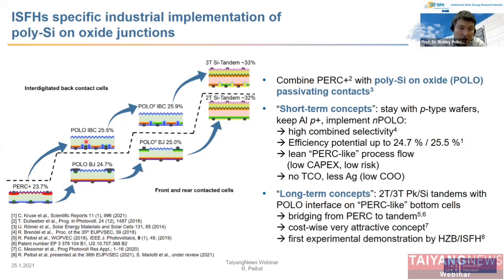And this should enable a high efficiency potential, as shown here with these numbers. Those are numerical device simulations for industrially feasible input parameters, in combination with a lean, PERC-like process flow, and in particular with a low silver consumption, because at least one polarity is still metallized with aluminum. This can be done either in this IBC version or in this double-side contacted version, which we call POLO back junction. And of course, eventually we're also working on long-term concepts, which are perovskite-silicon tandem devices.